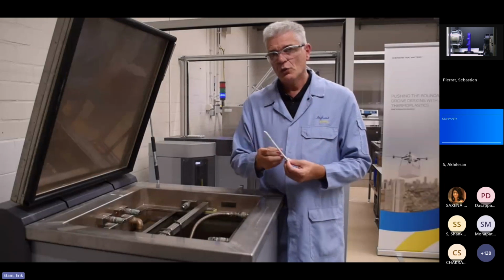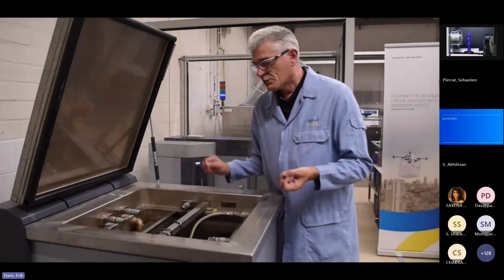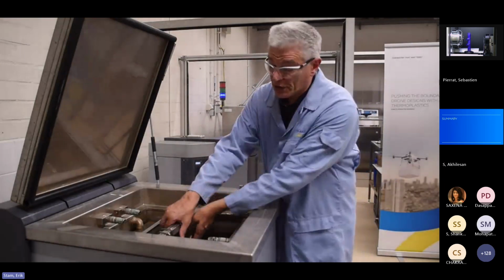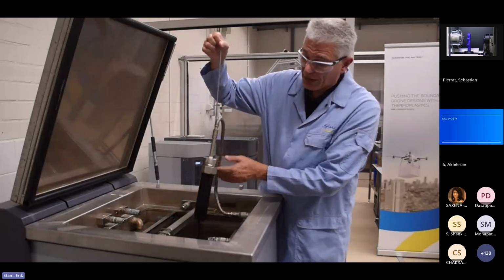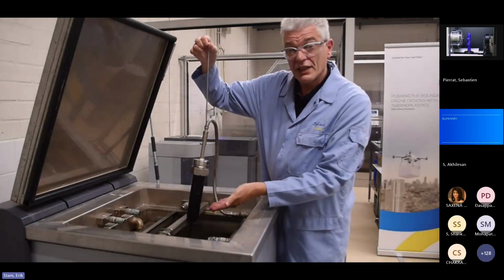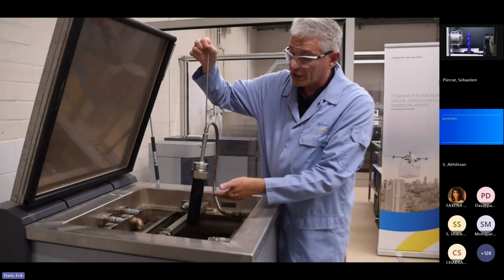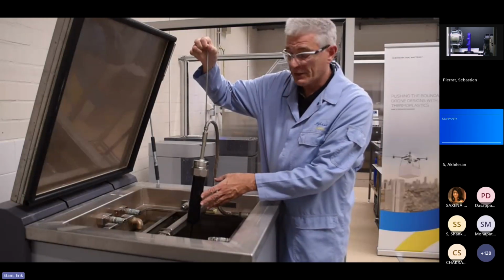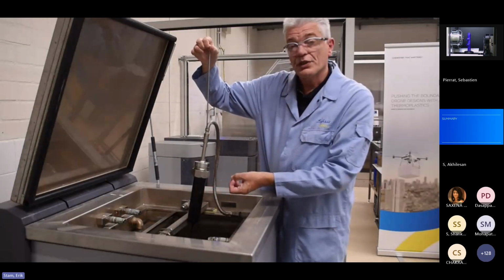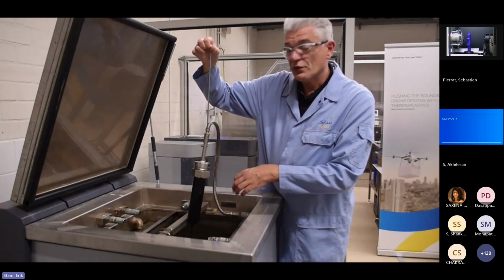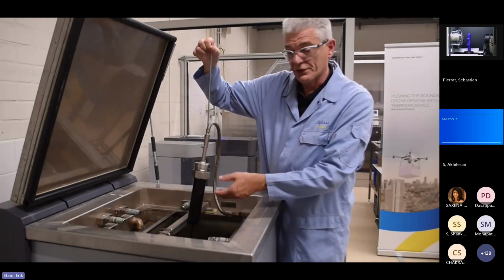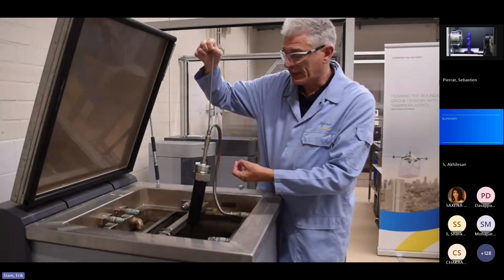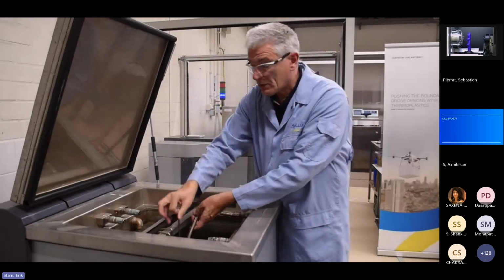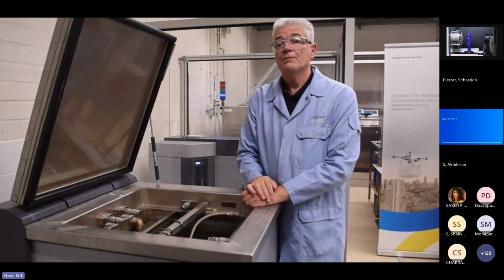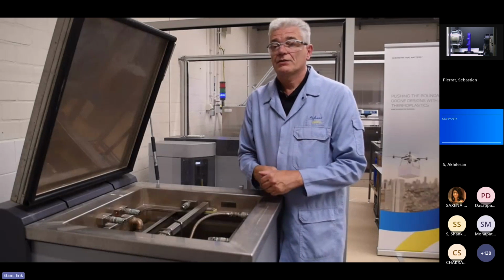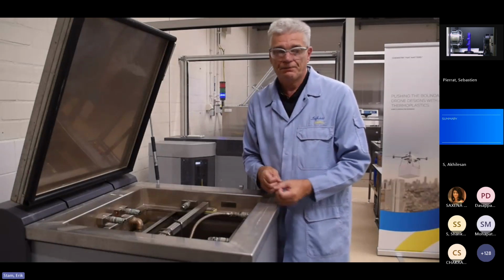we continue with more advanced testing. The first test we do on the application, or an example I will show you is an internal sample, is a burst test. In this case, a burst test means that you connect this to a water system. Inside is filled, and you increase the pressure with a pressure ramp, constant pressure rate, until the material of the sample fails. It can be this sample, but it can also be an application. We will now see a video of this recorded with a high-speed camera of a sample which is Noryl glass-reinforced material.